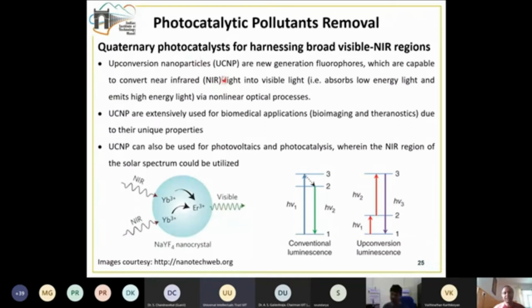Upconversion nanoparticles are new generation fluorophores. They are able to convert near infrared light, NIR light, into visible light. That is, they absorb low energy light and emit higher energy light by a nonlinear optical process. Basically, an upconversion nanoparticle consists of a lattice, a sodium yttrium fluoride lattice, which is doped with lanthanide ions, for example ytterbium and erbium. By tuning the identity of these lanthanide ions, we can tune the emission wavelength. When 2, 3 or 4 NIR photons fall onto the upconversion nanoparticle, internal nonlinear optical processes lead to the emission of higher energy radiation, in the visible light or sometimes even in the UV light.